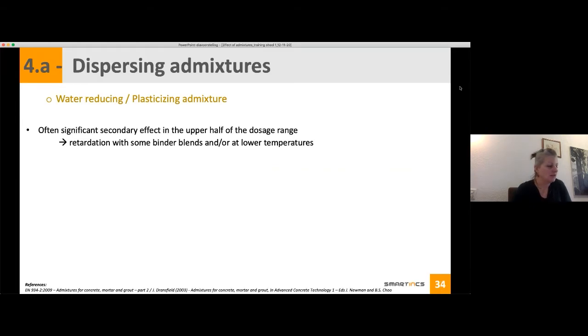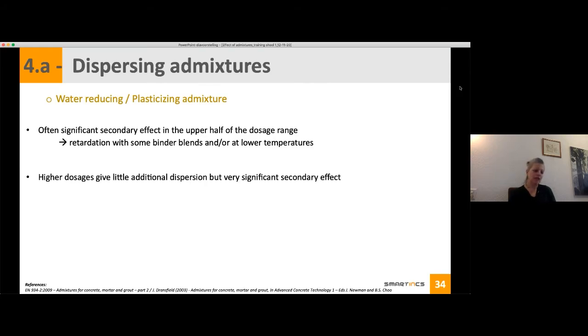That's why there is a mention here. If you have a dosage in a higher range, then you can have a retardation. It's also not the best admixture to use at low temperature. And if you are on the high range of your dosage and you say, still my dispersion is not high enough, you should take into account that a higher dosage will give very little extra dispersion, but really significant secondary effects, so more retardation. In that case you should go for another type of admixture, and then I would say a superplasticizer.